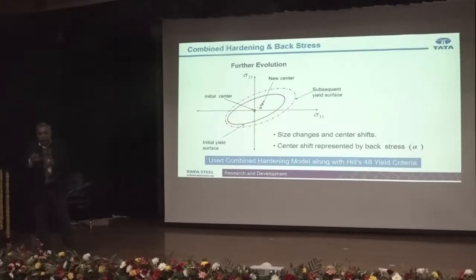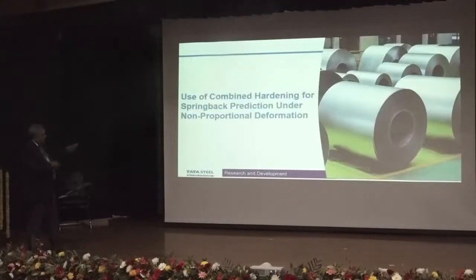And that rate of translation and the direction of translation will depend on the material and the deformation path. Then you have to devise some experimental procedure to characterize that, because you have to calculate the rate of translation and the direction of translation through some experiment, since the model itself will not work unless you give some material input. By the way, this is called the combined hardening model.